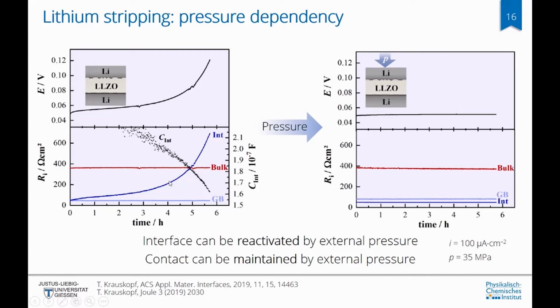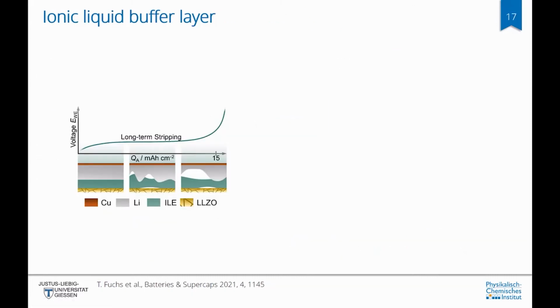Now, to prove that this is indeed the mechanical separation, this can be reversed by applying pressure, and we re-obtain the original low voltage for lithium stripping, and this low voltage can be maintained by having an external cell pressure on the stack. Of course, the application of an external pressure is not ideal for applications, which is why Till Fuchs in our group investigated what could happen if we include an ionic liquid interlayer between the lithium metal and the garnet. He managed to show that the stripping can be much prolonged, up to 15 milliampere hours per square centimeter, when using this ionic liquid interlayer.